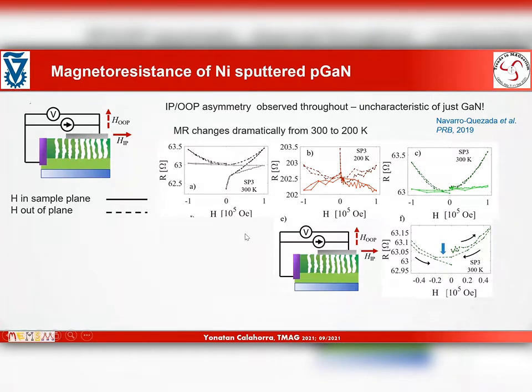Moving on to 200K from 300, the magnetoresistance changes dramatically. So the overall resistance increases, meaning that most of the current is carried not by the nickel, but actually by the gallium nitride layers. But now its characteristic is different. It's negative, although maintaining a difference between in-plane and out-of-plane. And then going back to 300K, we see that the low field features that we observed here are gone, but we remain with the in-plane, out-of-plane asymmetry, and also the sweep direction related control of the magnetoresistance